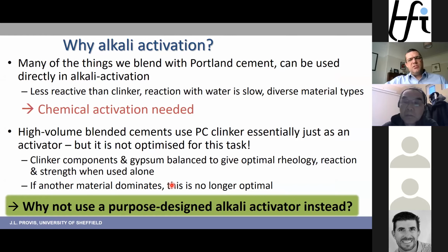They're diverse materials, mostly aluminosilicates, and they react with Portland cement because the Portland cement increases the pH up to pH 12, 12.5, 13 in a hydrating Portland cement. Very caustic environment within a reacting cement. That elevated pH starts the reaction of these supplementary cementitious materials. They contribute to strength development, microstructural development, and so on. If we just mix them with water, they go too slowly. So we need to activate them chemically.